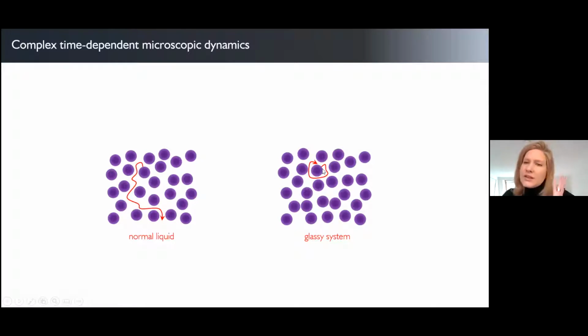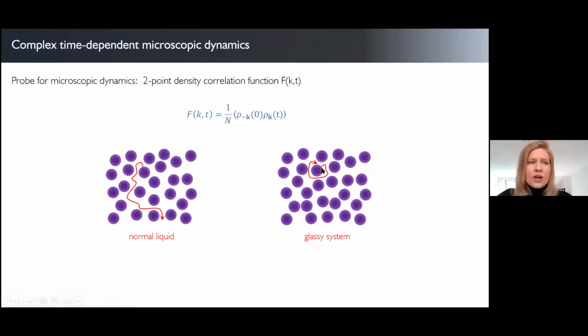And now, this more microscopic picture of the dynamics can also be quantified in different ways. And one of those ways is to look at something called a two-point density correlation function, F(k,t). This is also called the intermediate scattering function, and it's also something people can measure experimentally. So what this function measures is essentially the time-dependent version of the static structure factor. So it probes correlations in particle positions, both in space and in time.